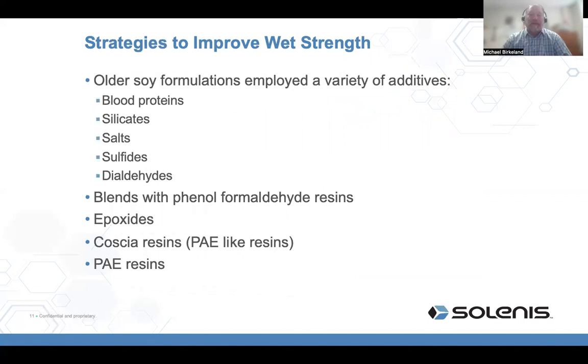Over the years, there have been a lot of strategies used to improve the wet strength in soy-based adhesives. The older formulations used a variety of additives. Blood proteins would be added for their coagulation or hydrophobic character. Silicates and salts have been added to improve ionic interactions. Sulfides and a variety of other chemistries have been used to try to modify side chains and get more reactivity. And then again, direct cross-linking with something like a dialdehyde also has been employed in the past.